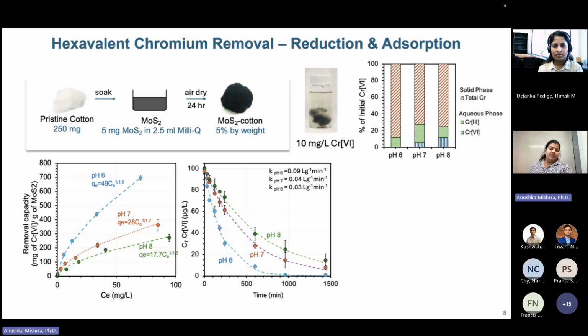The first effect that we saw is that pH had a big impact on how the chromium-6 is removed. So lower pH means higher chromium-6 could be removed by the media, and higher the pH, there was a drop in the removal efficiency, which means if we apply this material for drinking water purposes, which is usually neutral pH, we can see that a lesser amount of chromium is removed, maybe the material won't run at its maximum capacity.